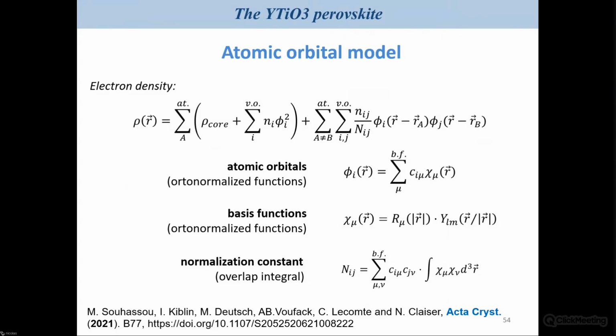In that case, you describe the electron density as a sum of two different terms: atomic centered terms, the first one, and the second one that introduces the bicentric contributions. The model is based on atomic orbitals. You see here the definition of them, which rely on basis functions made of the product of radial function and spherical harmonics. And we decided to apply a normalization constant, which is the one I just described there. So this is a model we developed for the study of these materials.